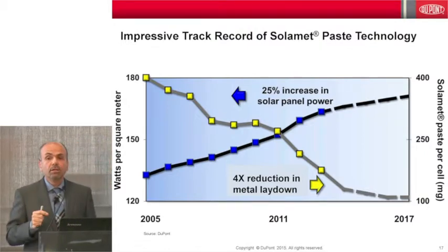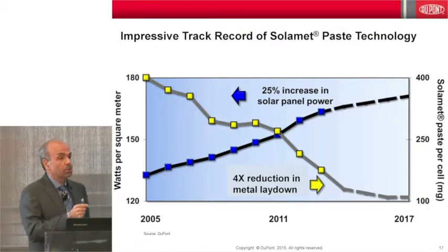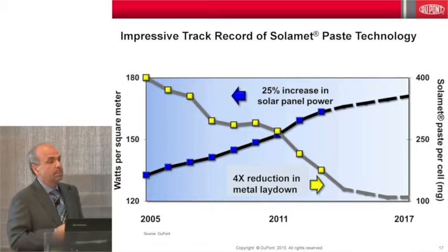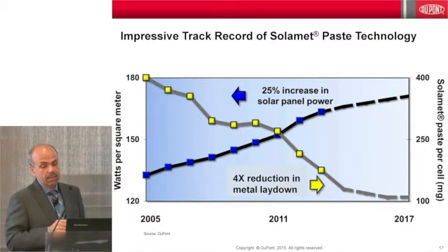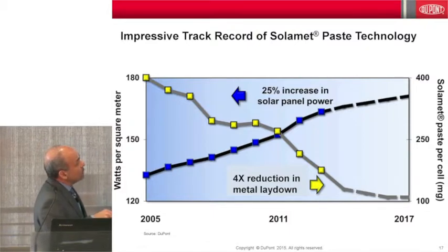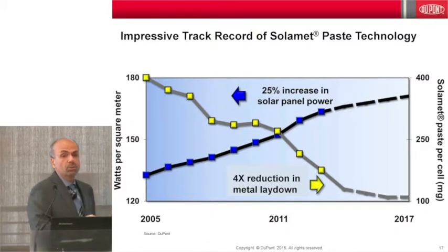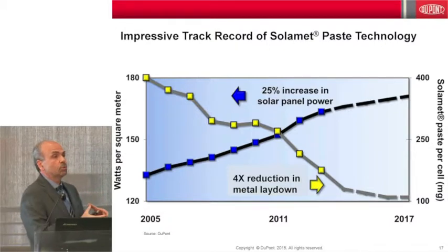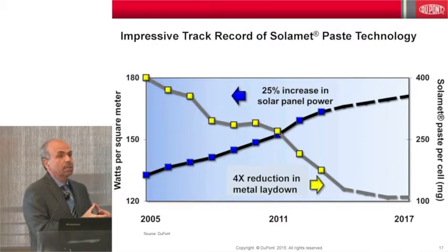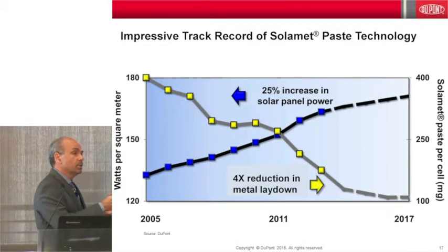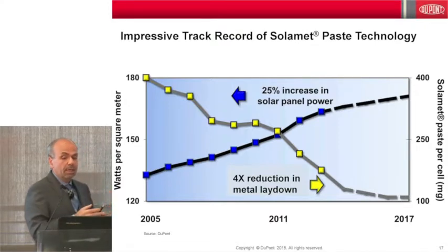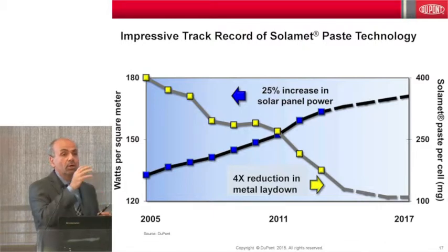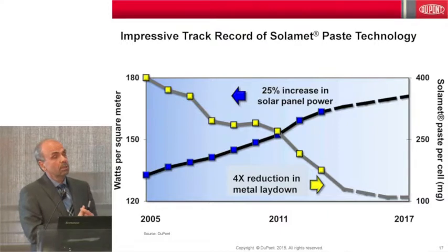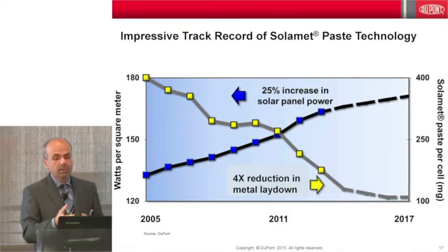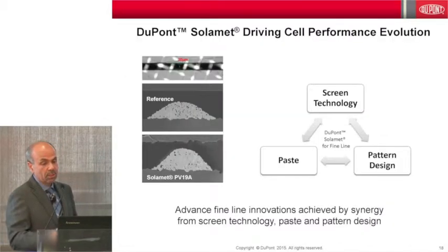And that came as a result of strong innovation within DuPont, but also a strong relationship with our customers. Jointly, we managed to bring down the cost of ownership as well as improve the performance of the cells. And at the same time, you see how the power density is going up and continues to go up as a result of this fine-tuning of the metallization. Some of you may recall that the cells used to be 5-inch squares or pseudo-squares, and now they're 6. They used to have 2 bus bars, and now they have 3, and eventually they will have 4 and 5. And although you are increasing the number of lines, you are reducing the silver as well as the shading, which 5 or 10 years ago was almost impossible to conceive. But again, innovation has delivered this solution.